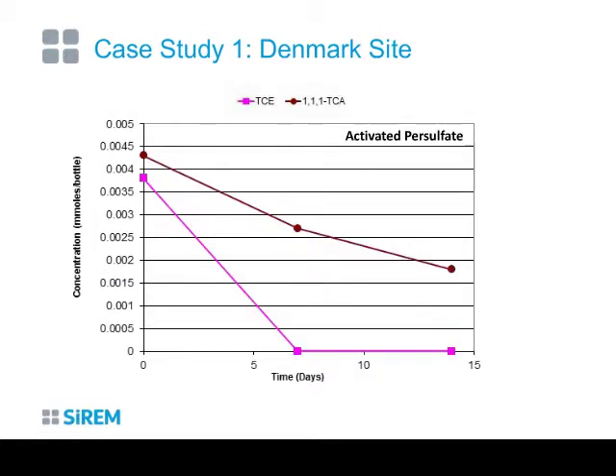And here are the results from an activated persulfate treatment. This was a much less intense study. We just did a quick snapshot after 14 days, and oxidant studies are typically very fast-moving and very quick. What we saw was that all the chlorinated ethenes were degraded by 7 days very rapidly and as expected, and that 1,1,1-TCA wasn't as rapidly degraded, nor did we see complete degradation with the consumption of the persulfate. Ultimately, the client went to the field with the bio because it was the best option to treat all the contaminant classes.